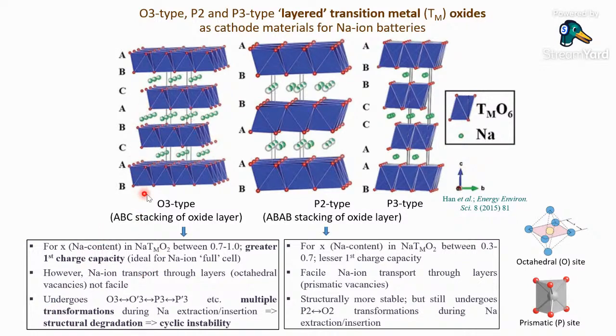Now, the disadvantage of the O3 type structure is again the air and water instability and relatively sluggish sodium ion transport as compared to the P2 type structure. And again, both these structures undergo multiple transitions during the sodium ion extraction and insertion unless something is done, and that leads to structural degradation in cycling.